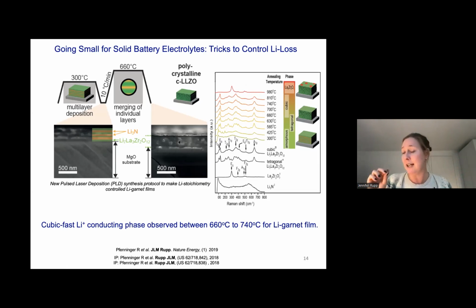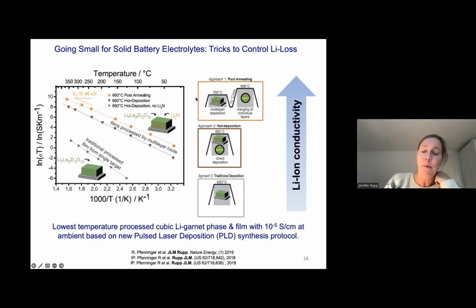So we have changed the field by offering something that could only be made before in about 100 micron or plus thickness at 1050 degrees Celsius sintering temperature. And we made it as half a micron with 660 degrees Celsius. So we just roughly halved the annealing conditions by the other processing, and we substantially decreased the thickness by a factor of 100. Now, what's the impact of that?